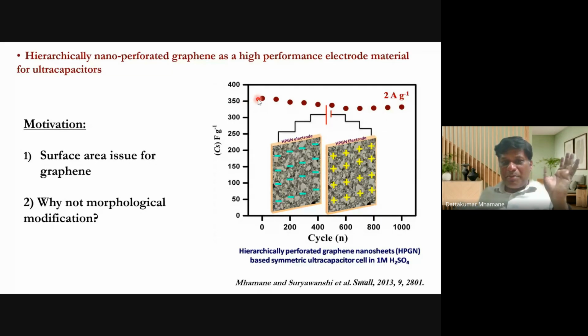You can see this device has delivered around 350 farad per gram specific capacitance at 2 ampere per gram, and this is the data up to 1000 cycles, and this is published in Small. So the motivation or the challenge behind it was that the surface area of graphene was too low, so we wanted to increase the surface area.